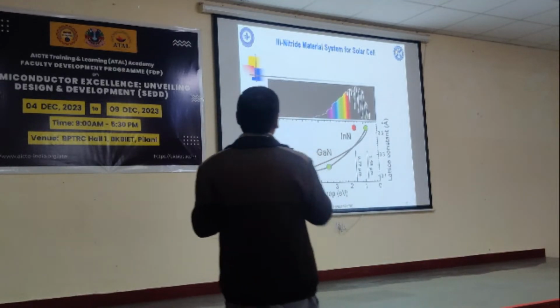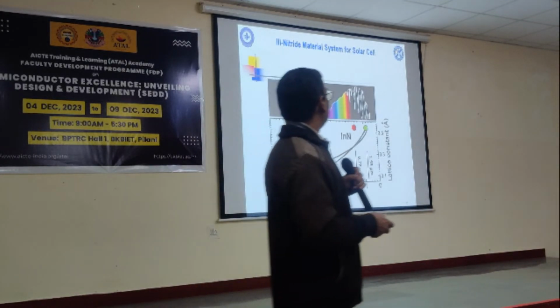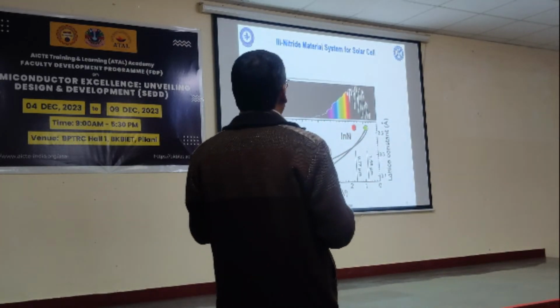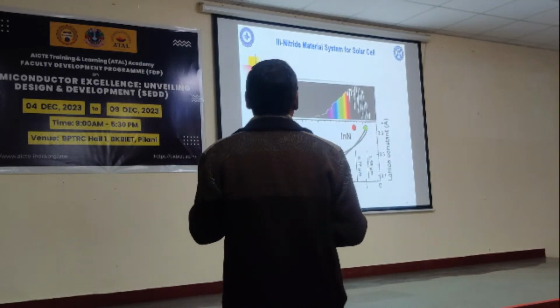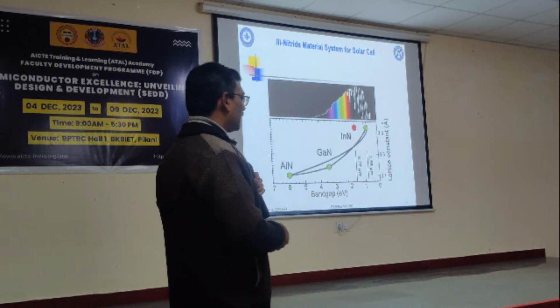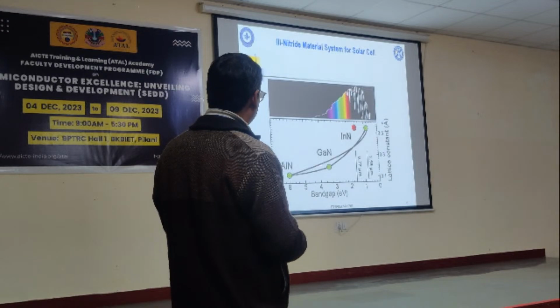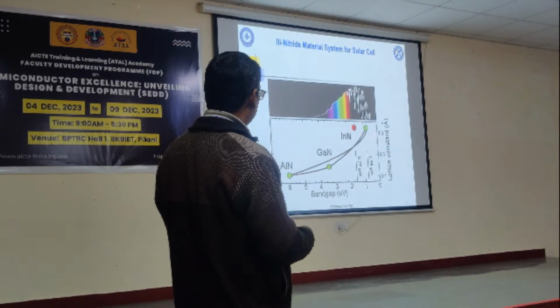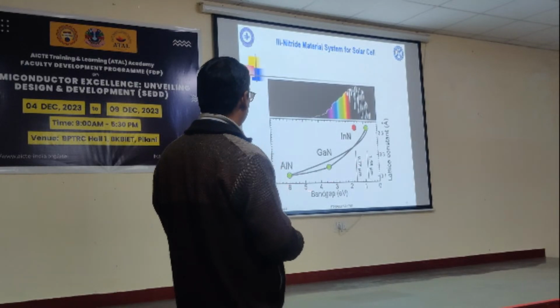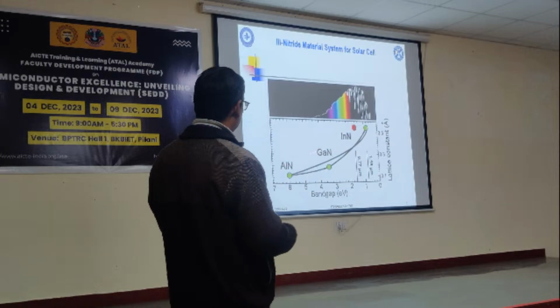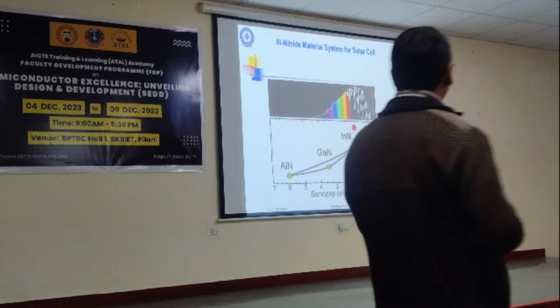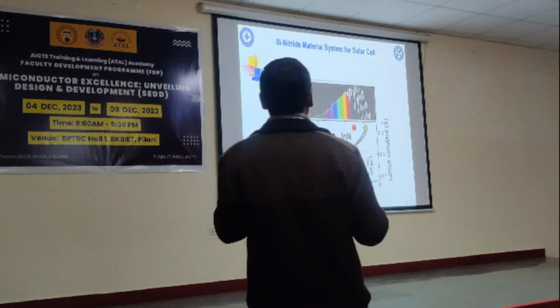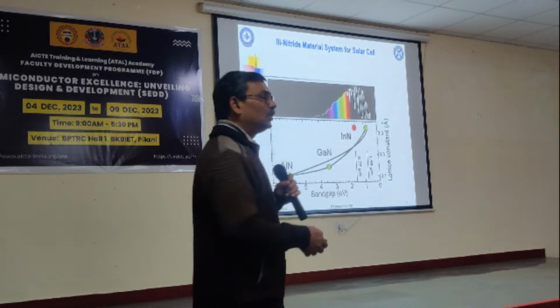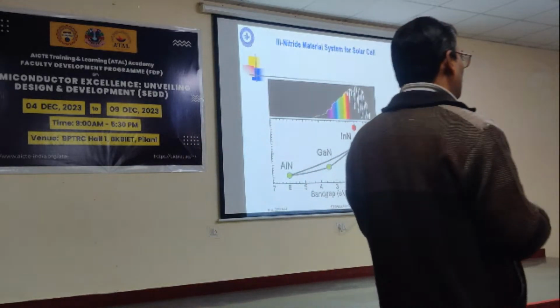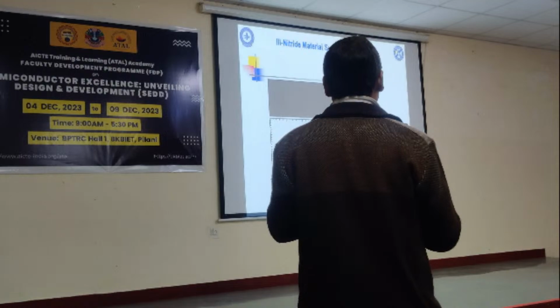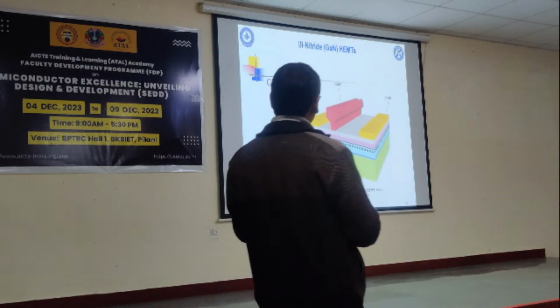This is another possibility. If we use that III-nitride gallium nitride material for solar cells, we can use the whole range of the solar spectrum. So that is the solar spectrum, and if we vary the aluminum composition to indium composition, you can see that from 6.1 electron volt to 0.67 electron volt we can consider. So theoretically, we can cover the whole solar spectrum to increase the efficiency of the solar cell. Practically there are some problems because of the indium or aluminum incorporation.